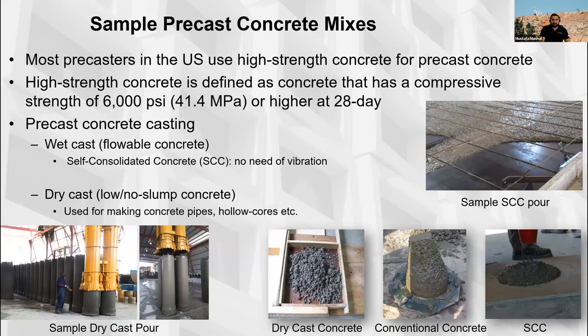So you can see conventional concrete slump versus dry cast, which is pretty much zero slump if you make a cone out of it. And then SCC, there it's super runny. And instead of doing a slump test, you actually do a spread test on it.